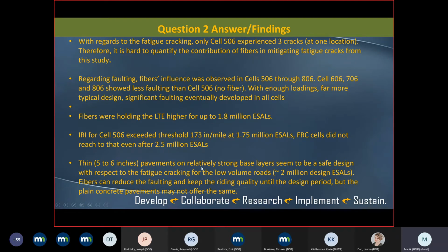So thin pavements on relatively strong base layers seem to be a safe design with respect to fatigue cracking for low volume roads up to 2 million ESALs. Fibers can reduce faulting and keep the riding quality until the design period, but plain concrete pavements may not offer the same. So we saw cell 506 reached the critical value of 173 even before 2 million ESALs.